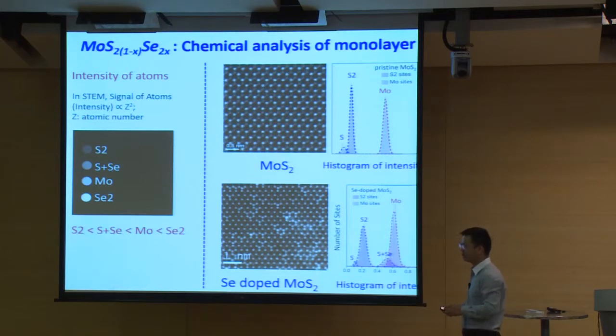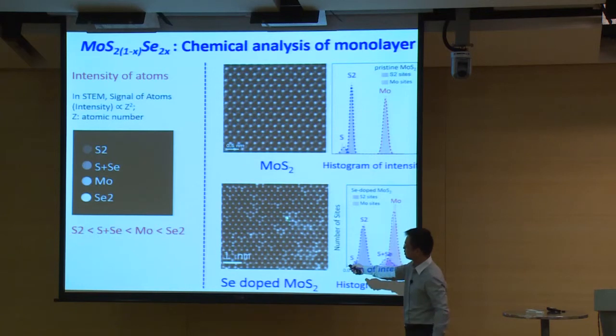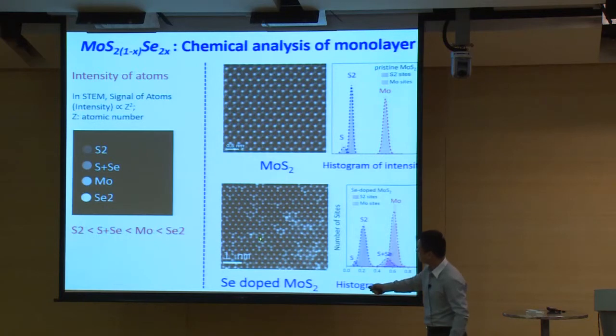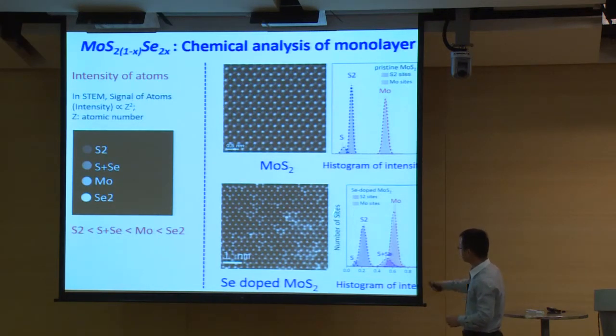Okay, what will happen if we dope selenium to this system? You can get these very bright areas. So this is double selenium, 2 selenium atoms. And some areas not that bright. This is selenium and sulfur. And the very dark side, there are 2 sulfurs. And this periodic bright side, the moly. So we can also get the histogram of the intensity distribution of moly, selenium plus sulfur, 2 sulfur, 2 selenium.